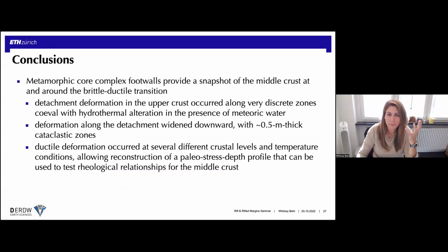So to conclude, metamorphic core complexes provide a snapshot of the middle crust at and around the brittle ductile transition. And then the observations of the structures within them tell us about faulting behavior in the upper crust and down into the middle crust where the faults interact with more distributed ductile shear zones. And quantitative analysis of stress and temperature from microstructures preserved from different structural levels within these core complexes allow us to reconstruct stress depth profiles that then support the idea of a relatively strong middle crust, or a peak in the Christmas tree in continental regions. Thanks, and I'm happy to take questions.